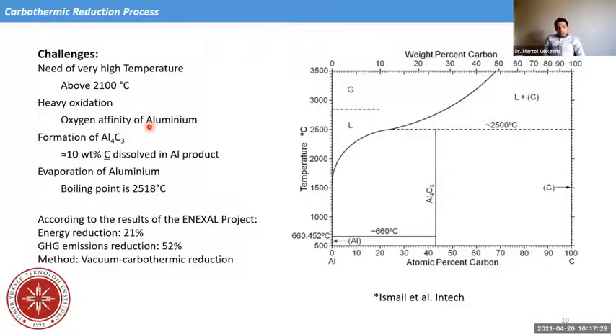And the third challenge is formation of aluminium carbide. Carbon has solubility in aluminium. At aluminium processing temperatures in the melt treatments, around 700 degrees, it is not much. Then we can talk about easily below 40, 30 ppm of carbon dissolved in aluminium. But you can see here that the solubility significantly increases with temperature. And when it comes to the production temperatures of the carbothermic process, in case we want to do it, it easily reaches 10 weight percent and 20 atomic percent of carbon dissolved in aluminium.